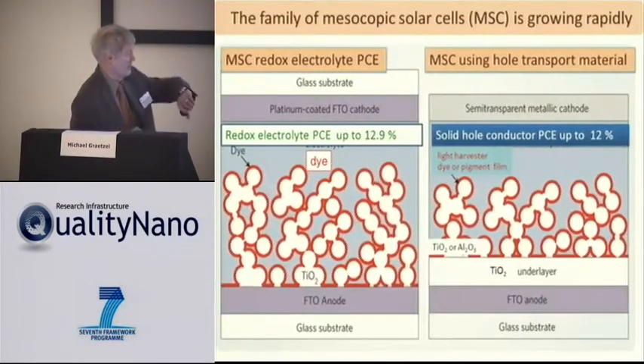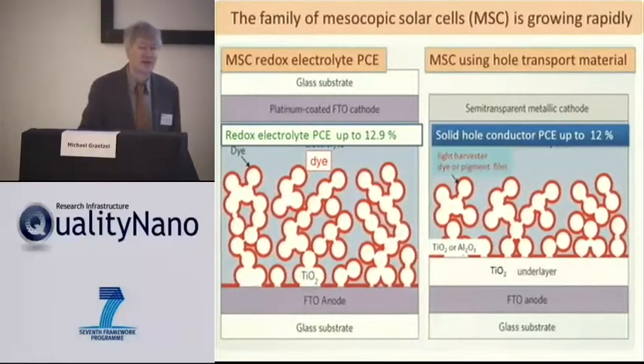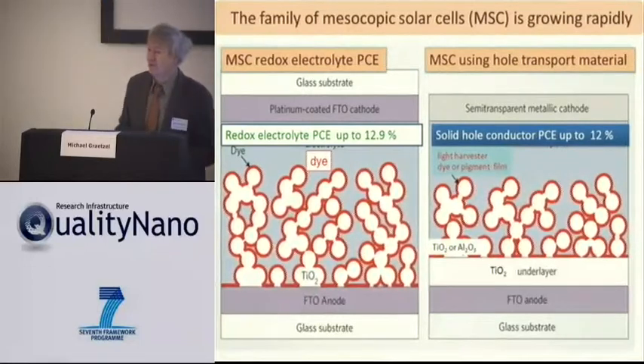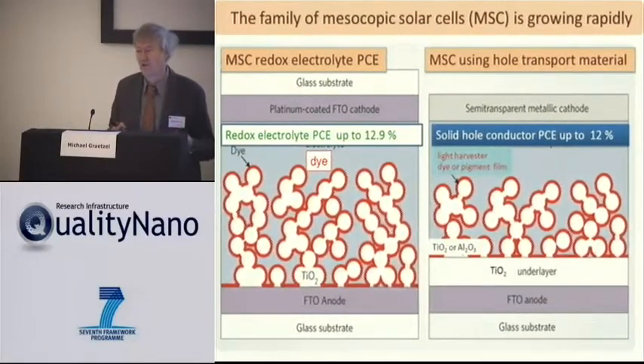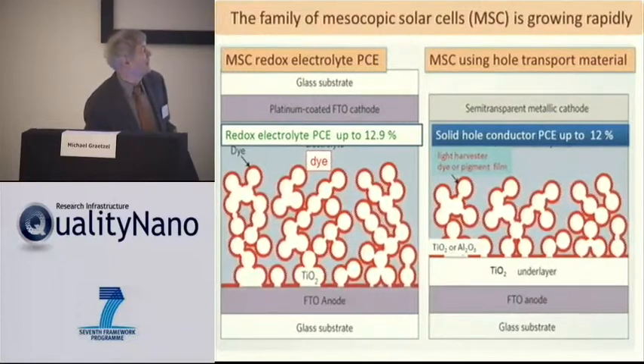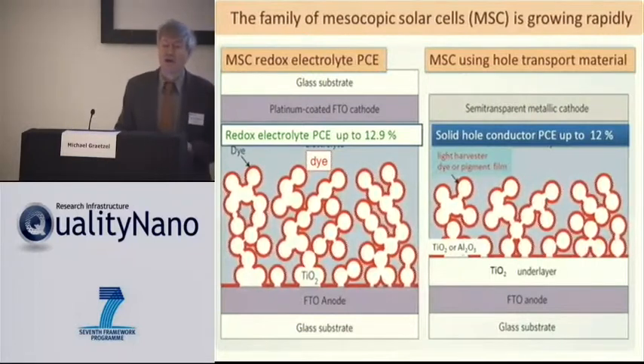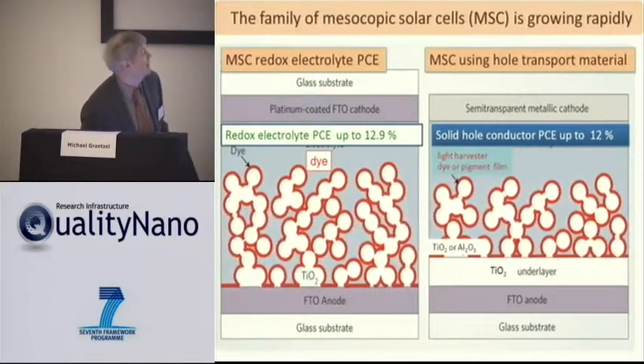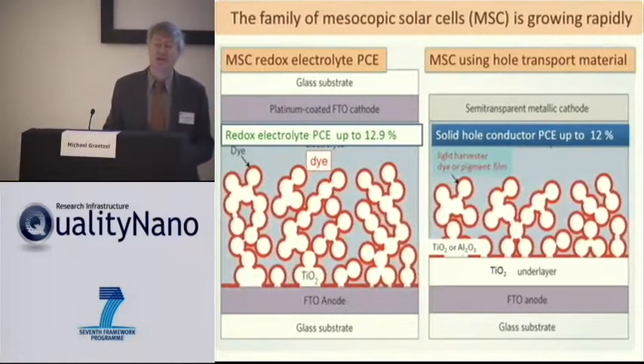Just wanted to mention one more highlight of our research before I show you some applications. And so this is now another embodiment of the mesoscopic solar cell, which is solid. There's no liquid. Okay? And so I'll show you how that is made. Well, again, we have the nanocrystalline film and the dye, but now comes a new feature. Pigments are being employed. Small pigment nanoparticles, or small pigment particles, they are in the nanometer size range. And so these pigments have a higher optical cross-section than the sensitizer.